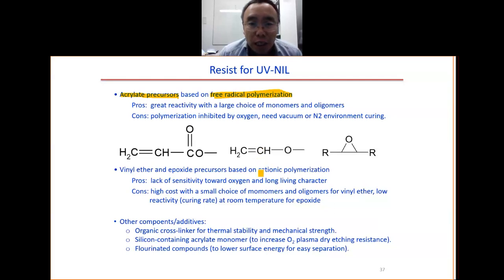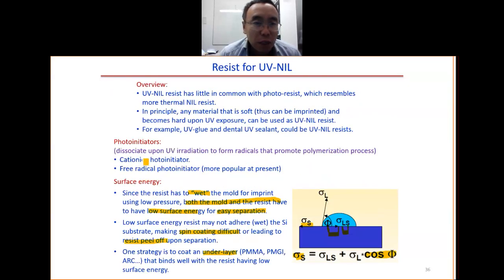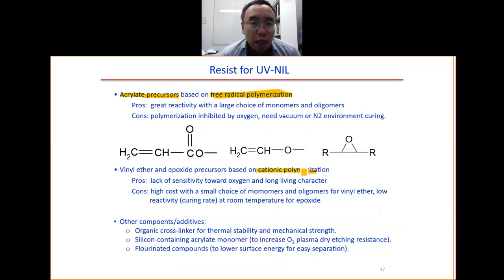This is the free radical polymerization. Another one is the cationic photoinitiator, or cationic polymerization. There are two choices. One is the vinyl ether, and the other one is the epoxide. The advantage is that this one is not sensitive to oxygen, so we can do the UV imprint in air. The problem for the vinyl ether is that the cost is high, and there is a smaller choice of monomers and oligomers. For the epoxide, the curing rate is low at room temperature. So those are the main components of the UV resist.